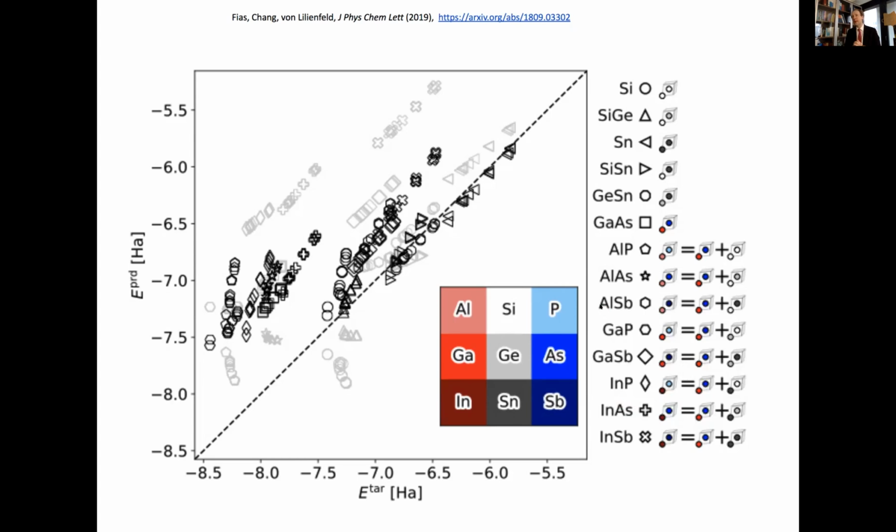So by this, you can also see we can easily extend our alchemical normal modes to work not only in Z, but actually in any other measure of chemical compound space. It's more general than Z. It's really just a lambda coupling parameter, which you can exploit. And this is what you see here. Now what do you have in the main graph? It's a scatter plot, second order estimates, according to these normal modes, starting from germanium. We always use germanium, and we predict all these other materials. There's an estimate of the formation energy, the true energy versus the estimate, and in black you have the second order estimate, in gray you have the first order estimate. So you see on average a dramatic improvement when going from first to second order.